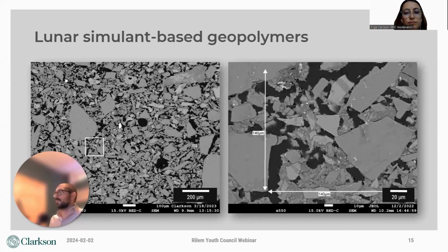Practically, that means either the activator is a poor choice and perhaps a stronger concentration would lead to better polymerization, or the simulant might not be very reactive, indicating that lunar soils with this kind of composition are not suitable precursors for lunar concrete. Based on that, we could guess which regions of the moon could be mined for geopolymer precursors.